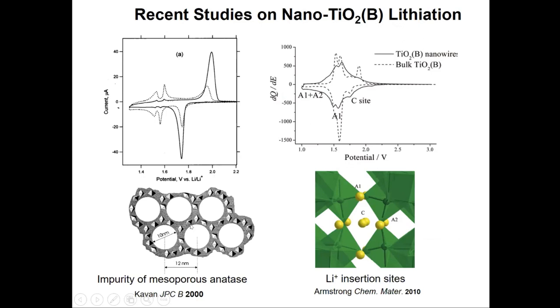And then later on, Peter Bruce, another well-known battery expert, claimed by using theory that this TiO2-B nano was a very good battery material. And then they tried to use, I would say, not quite an adequate level of theory, and claimed again that in this TiO2-B, the first site that filled was the C site and then A1 and A2. But we now know that this peak right here, because of its potential, is really the anatase impurity, because